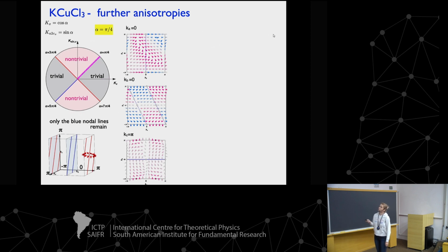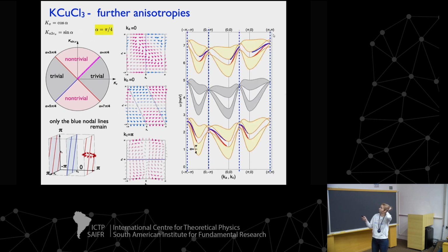So then we can go to this boundary, when we are on one of these, in this case, the blue, the nodal lines are still there. And then as you can see along these lines, we actually have a vanishing D vector. So those are these white points in the figure where the D vector is actually 0, so I can't really plot a vector there. And in this case, as you can see, these degeneracies are actually surviving. So we have a nodal line type of phase.